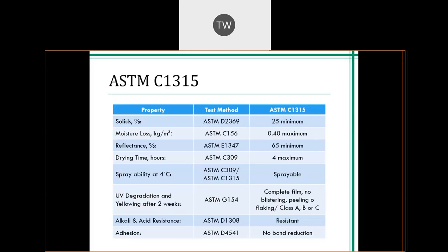These are the performance requirements of ASTM C1315, and it should become quickly apparent that it is a more stringent specification than ASTM C309. It has a 25% minimum solids requirement. It has a 0.4 maximum moisture loss requirement. It has a 65% minimum reflectance requirement. It has a UV degradation and yellowing after 2 weeks requirement. It has an alkali and acid resistance requirement. And then finally, an adhesion requirement.